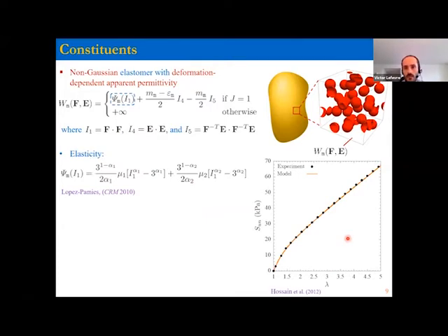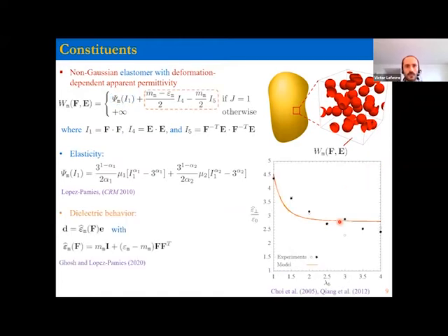And on the right, you have a comparison between the model and some experiments, uniaxial tension results. They were done for a typical dielectric elastomer. It's VHB 4910 from 3M. The second part of this total free energy is characterizing the dielectric behavior. And so here, this choice represents this type of model to account for the fact that the permittivity of the dielectric elastomers may depend on the stretch. So this is a comparison between the model and some experiments for this same dielectric elastomer. And it's not perfect, but gives a good idea of the trend of what people have observed experimentally.